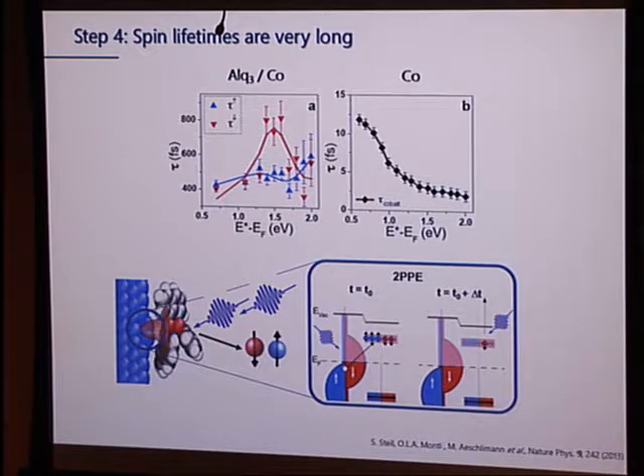This follows Fermi liquid theory. And so this is an extraordinarily long lifetime of a carrier at a metal interface. You would expect it to be quenched very quickly because of energy transfer into the bath of all electrons that are residing in the cobalt. So something really slows down that lifetime. And, of course, that is another hallmark of interaction between the molecule, which has a much different density of states and different electron correlation, and hybridization of that with the surface.